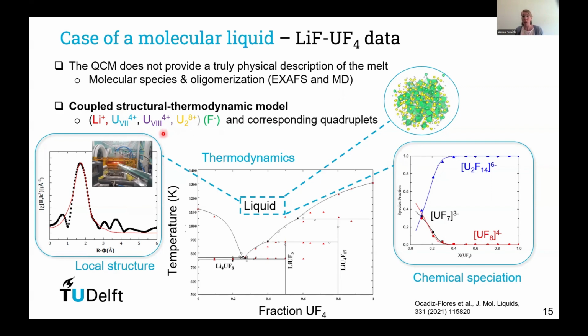And when we increase uranium fluoride concentration, we start to form dimers. So we made a model of that system that included 7-fold coordinated uranium, 8-fold coordinated uranium, as well as dimers, which we could say represents the formation of polymeric chains at high uranium content. In this way, we can have a thermodynamic model that reproduces phase diagram information, but also gives